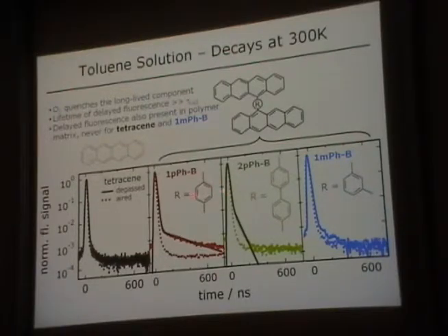But with these bis tetracenes, at least with the para-linked, para-biphenyl, and paraphenyl, with and without oxygen, you clearly see a long delayed fluorescence component, almost a microsecond for the single phenyl, much shorter for the biphenyl. I don't think I'll be able to get into those details. Again, nothing detectable really for the meta-linked phenyl group. Okay, so 2 out of our 3 worked. You see this delayed fluorescence component. It says that this triplet pair is lasting for about a microsecond. You create it, it sort of sits around, and then it recombines and generates fluorescence.